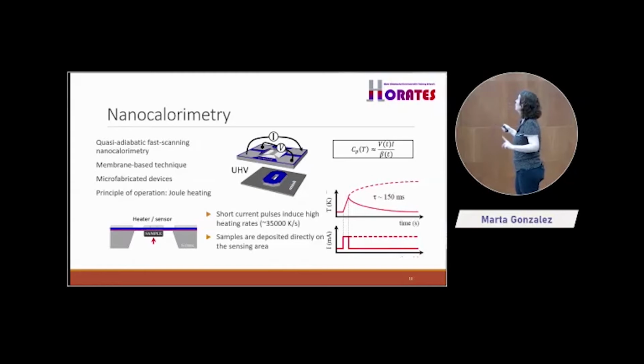So yeah, one more thing. This is a pulse of about 35 milliamps, something like that. It depends what you need. And since the system is that thin and its thermal mass is so small, you can achieve heating rates of around 10 to the 4, 10 to the 5 Kelvin per second, okay? The idea of going that fast is also that we don't provide time enough for the heat of the transition and the one that we are providing to spread into the rest of the system, to the membrane, to the frame. We don't give time enough.